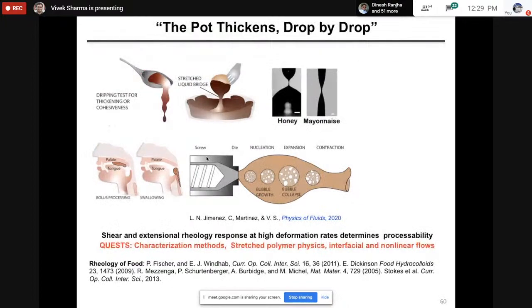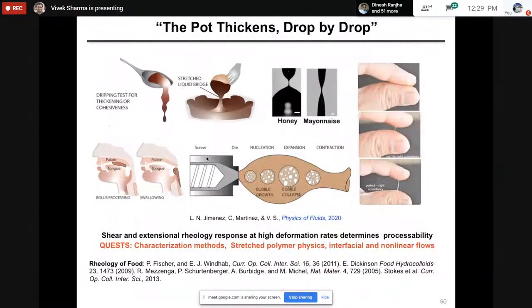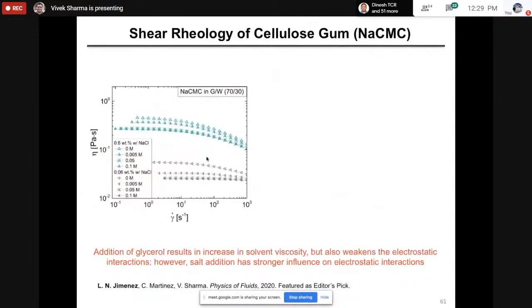The last example I'll give you is of cellulose gum that's used in food rheology. And here we are looking at cellulose gum in a glycerol water mixture. And cellulose gum is a charged polymer, so it shows some sensitivity. The shear rheology shows a lot of sensitivity to amount of salt. And again, to understand this, it's a charged polymer. In absence of salt, chains are stretched out. So you get coil overlap to happen at much lower concentration.